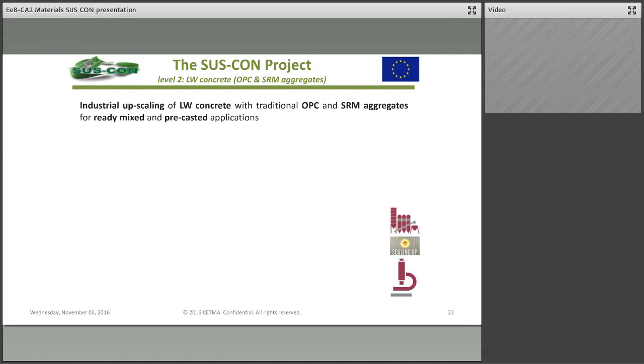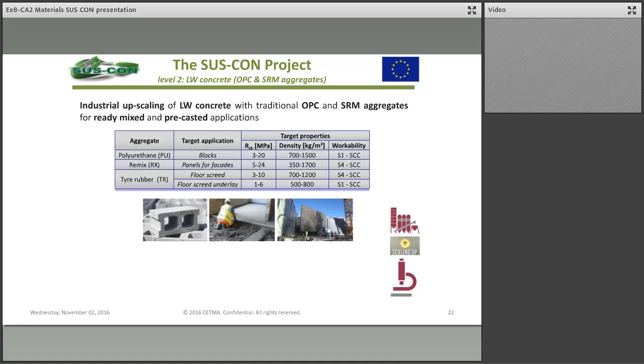The next step was the industrial upscaling of lightweight concrete made of ordinary Portland cement and aggregates from secondary raw materials for ready mixed and precast application. To this aim, we set the target performance that we had to obtain for the target applications that were blocks, panels, and screed, floor-screed and floor-screed underlay. So a parametric study was performed in order to optimize cement content, aggregate content, water to cement ratio, additives, aggregates proportioning, and so on.